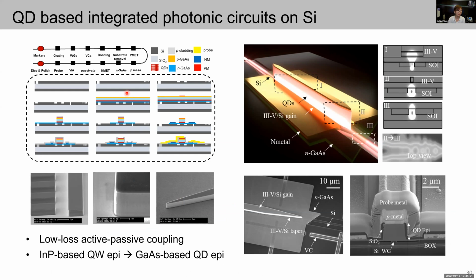So the process starts with the passive waveguide process, the subsequent wafer bonding and substrate removal, and then we etch the III-V mesa precisely down to the 150 nanometer n-GaAs contact layer and try to keep the etch uniform across the whole wafer. So a lot of process optimization was devoted to achieve smooth, straight sidewalls so that we can get this very nice III-V taper to shape the hybrid active mode to couple into the passive silicon waveguide mode on both ends. And after patterning the p mesa, a separate short lithography was done to pattern this n-GaAs contact layer. And then after that, the metal stacks were deposited and the device was passivated and the via was opened for the probe metal deposition.